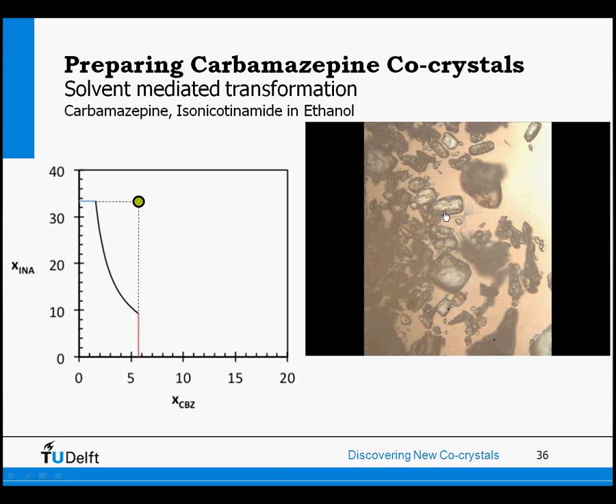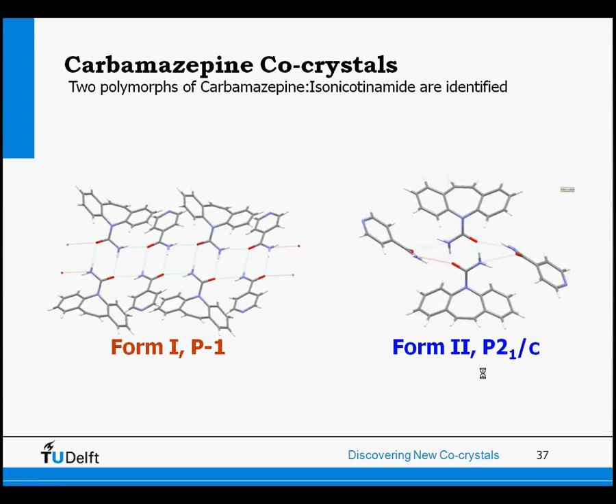But at some point also these needle crystals start to dissolve, and other crystals pop up somewhere else in this view. So actually what we discovered is that we have two polymorphic forms, so form 1 and form 2. And in the movie, which you did not see, we see first the form 2 appear, that is the needle form, which then later on transform into form 1, which is the final stable form at room temperature.